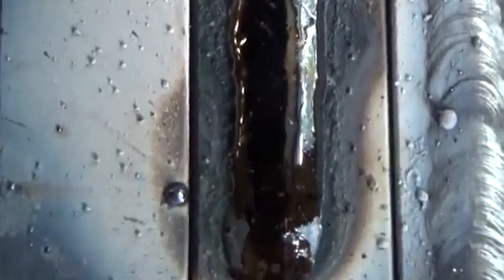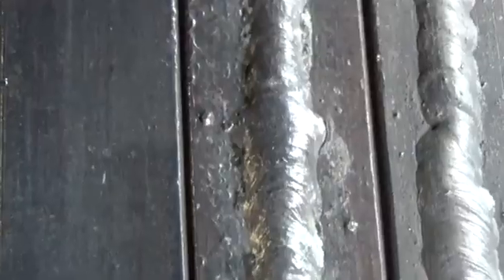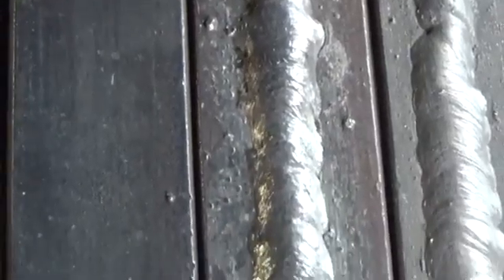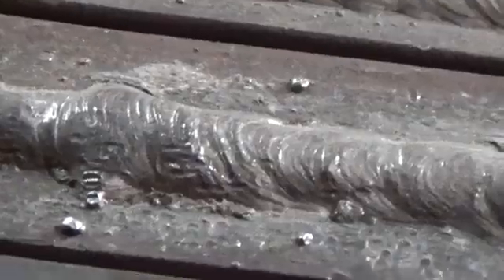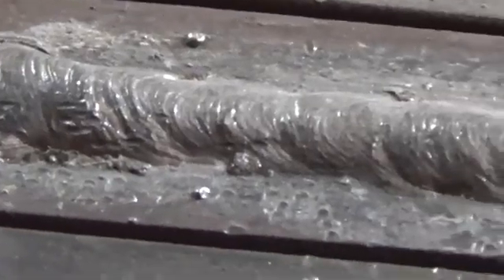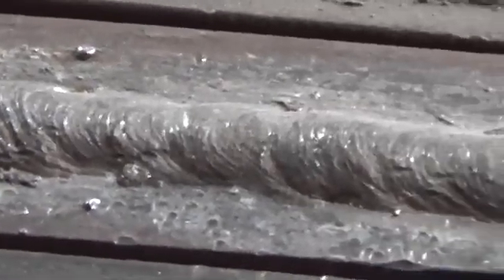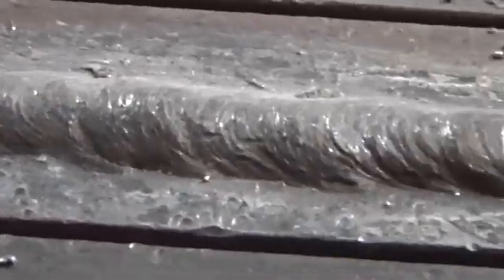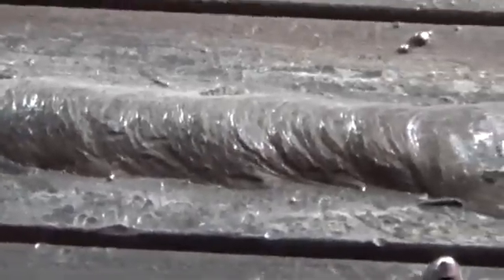Here, as well as at the beginning of the weld, defects occur more often. Let's clean off the slag and look at the weld. The seam has a regular geometric shape with a flat top and a smooth transition to the base metal. This form of weld is obtained by a proper combination of the welding current, the welding speed, the electrode slope, and the length of arc. The last weld, electrode positive, welding current is 90 amperes.